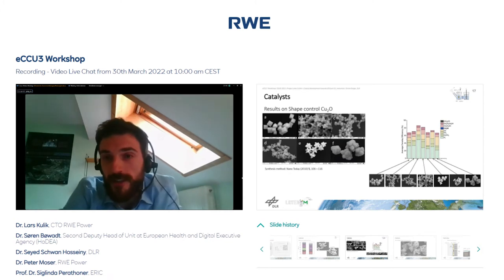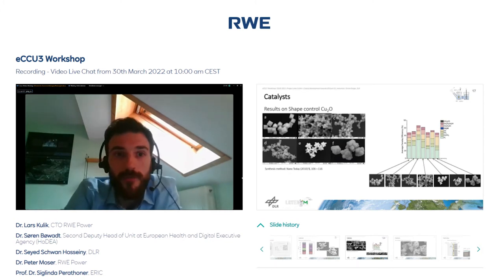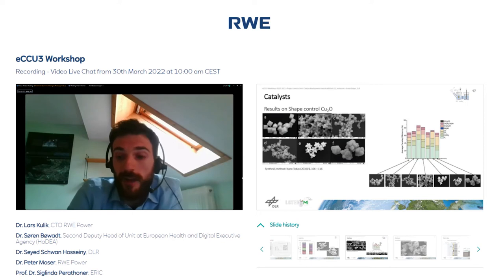On slide 17, this was also shown by Schwan this morning briefly. We synthesized ourselves different shapes because we thought, okay, we saw this shape have some influence since the octahedra produced some methane before, and we produced a bunch of different shapes and compared the Faradaic efficiency. However, one would need to say that within the error bar, the shape was not that decisive, and also the product did not significantly differ from the commercial one. So we are still working now with the commercial product because we have this in large scale available.